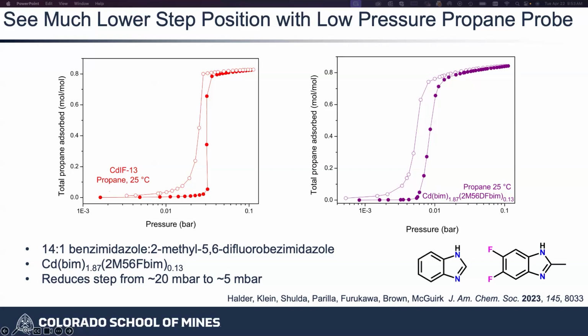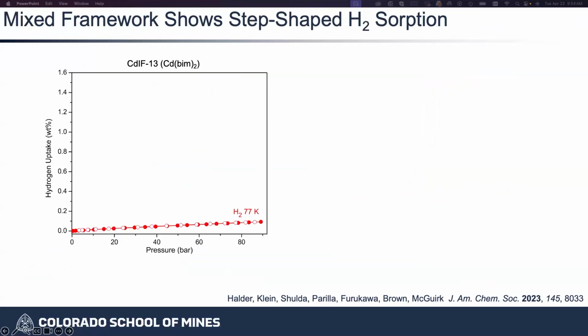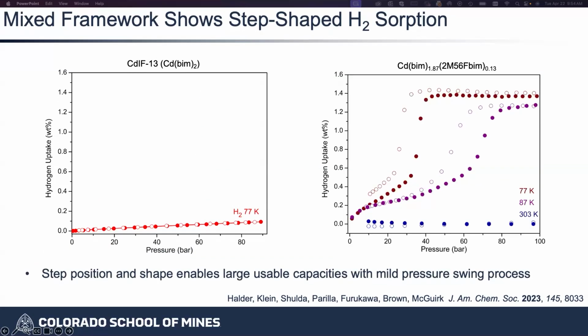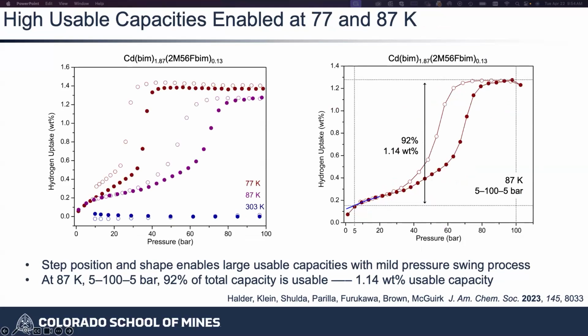Now with this doped system, you can see that the step onset is at an appreciably lower pressure over here. And that told us that we could go back and do the hydrogen measurements again, because those high pressure hydrogen measurements are hard to do. So again, here's the original system. And now with just about 7% of another linker doped into that lattice, we can see that the pressure response completely changes. And going back to that original motivation, if we do these pressure swing situations, so much of that total capacity is now being captured in that usable capacity.